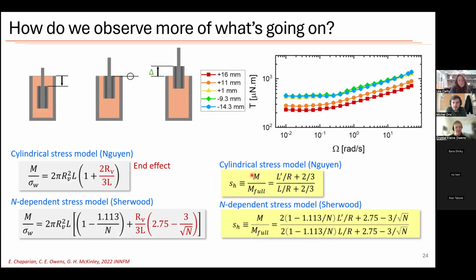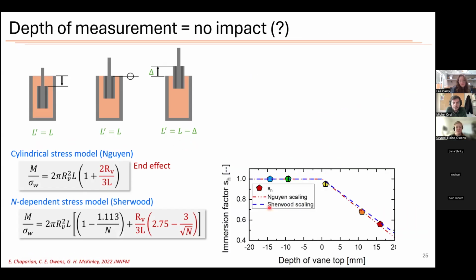These just use the ratio of the torque that you would expect on a vane that is incompletely submerged, that is, something with partial submersion, compared to something that has full submersion. And so, for example, if you have a vane that is under or at the surface, then there's no change here. If you have something that's a little bit above, then this value starts to decrease. So the shift factors would look like this, where as long as it's below the surface, it's about 1. And then as it goes down, you see less and less torque just as the vane comes out of the surface.